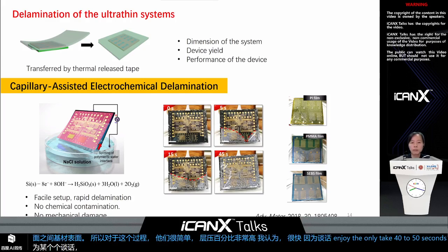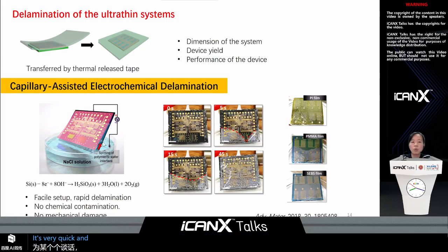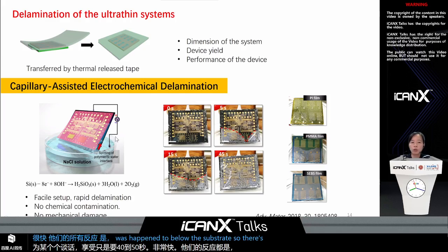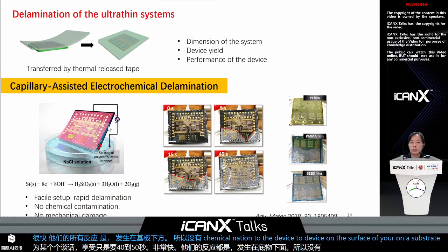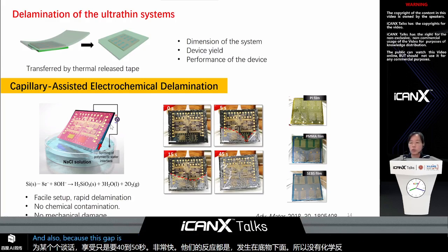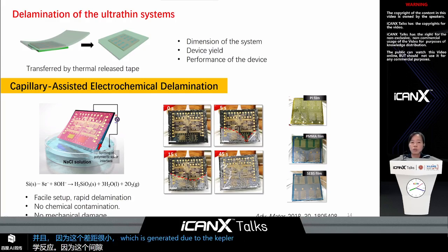It's very quick. And as all the reaction happens below the substrate, there is no chemical contamination to your device on the surface of your polymer substrate. And also because this gap is very small, generated due to the capillary effect, there's no mechanical damage to your device.